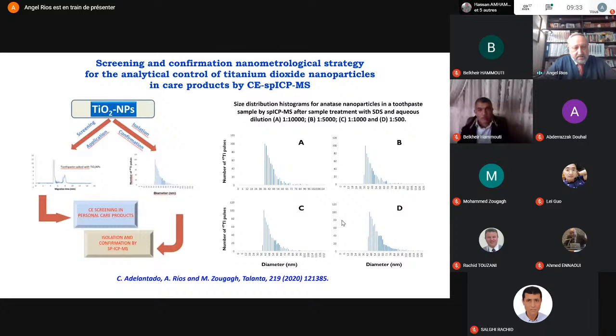In this case, the capillary electrophoresis method allows the screening of the titanium dioxide in the sample, and then the confirmation, after the isolation of the component in the sample, of the size of the nanoparticles present in the sample, as you can see on the right side of the slide.